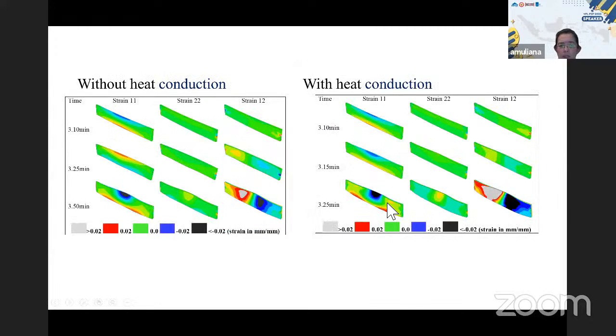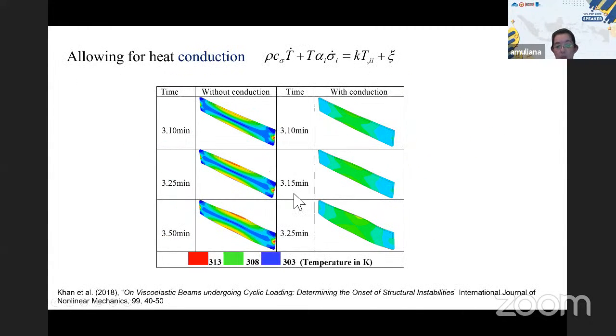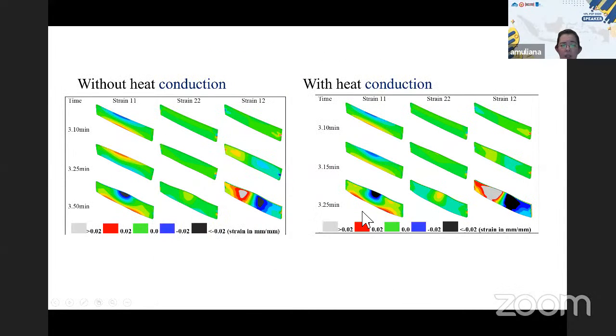While this response is the temperature increase, this I'm just showing you the strain response of the strain component. So localized strain you will see at the later time, right? As the polymer gets softer, it undergoes larger deformation. So that's where you start seeing all this failure or instability in the component.